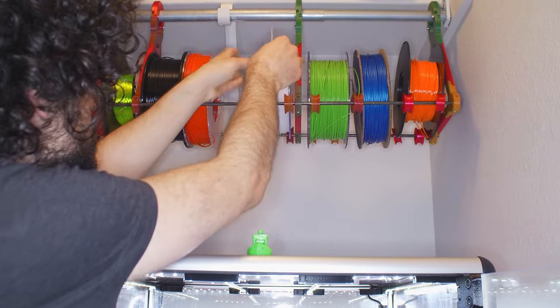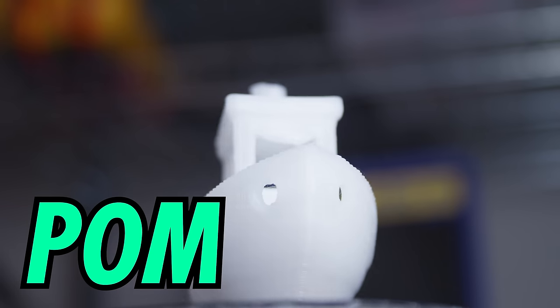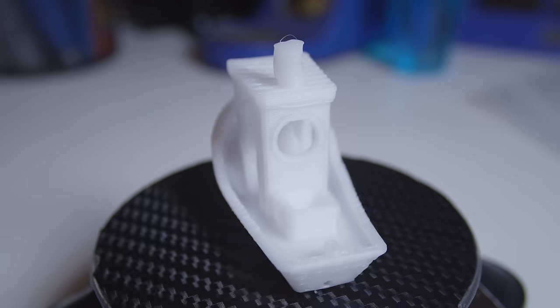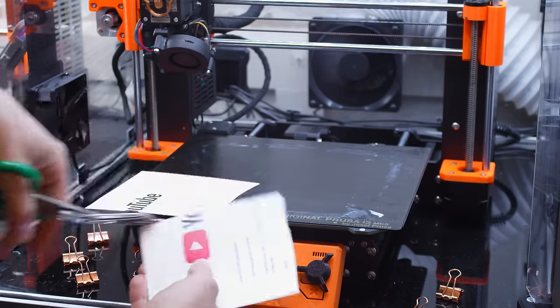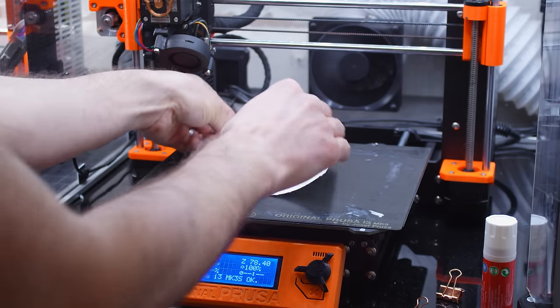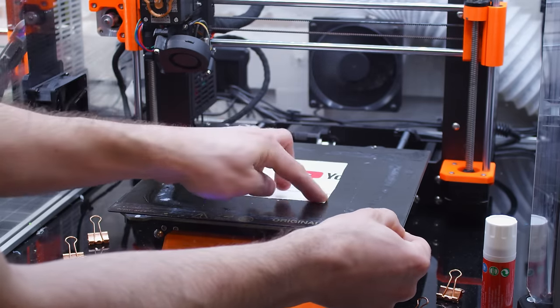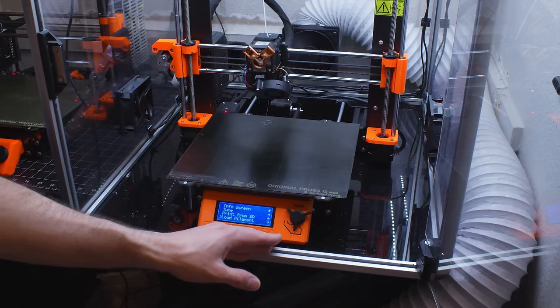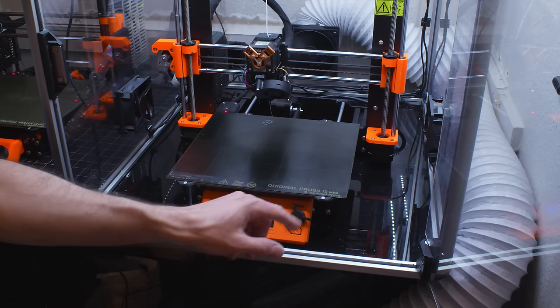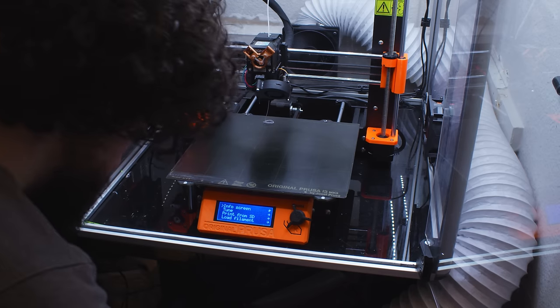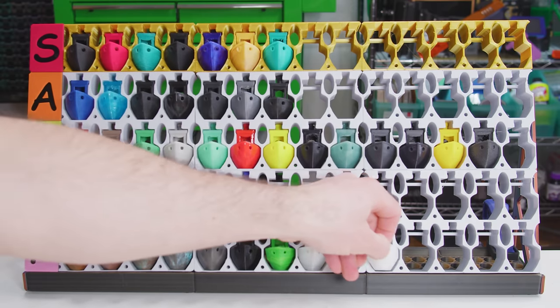HDPE's bed adhesion is one of the worst, but if you want the absolute worst, you want polyoxymethylene, a.k.a. acetal or delrin. I don't know why you would actually want that, but here you go. Every CNC user is familiar with POM. It's this cheap, usually icy white resin that's super stiff, super easy to machine, and has a remarkably low coefficient of friction. POM has literally zero bed adhesion. You have to glue a wooden board or a sheet of rough paper to your bed and lay down the first layer so aggressively, it embeds itself into the fibers. Like, it needs a mechanical connection to stay on the bed. POM's layers really want to split apart, so you have to heat the enclosure and go as slow as possible. There are two more giant problems with POM. Anything it can do, nylon can do cheaper and easier. Second, if POM gets a little bit too hot, it degrades into the corpse-preserving cancer-causing toxin they call formaldehyde. The name polyoxymethylene is actually a euphemism because polyformaldehyde sounds too scary. For that reason alone, I'm going to put POM in F tier. F for formaldehyde.